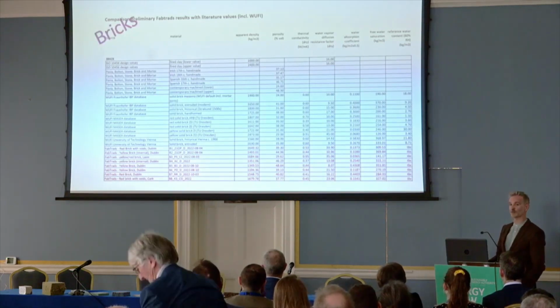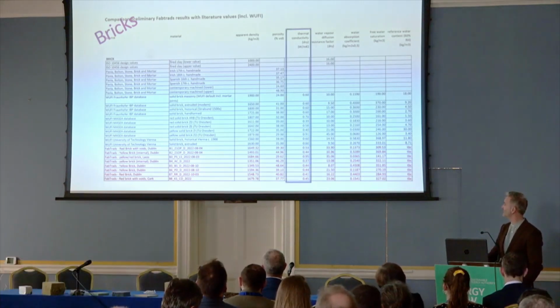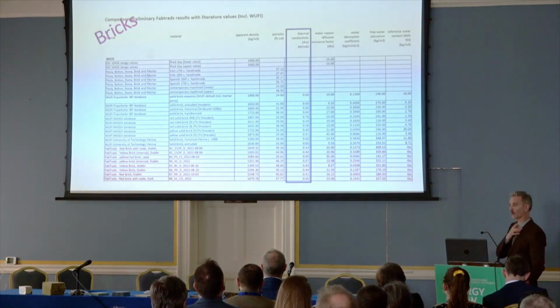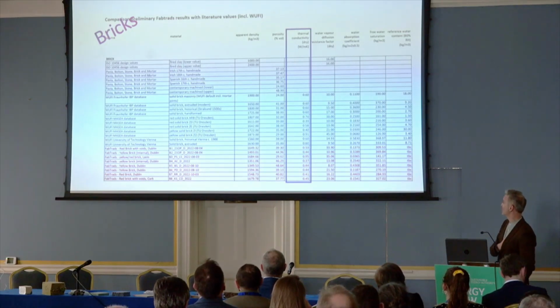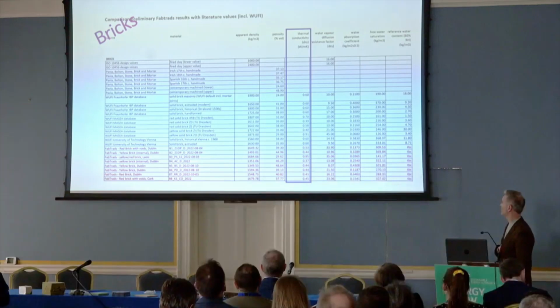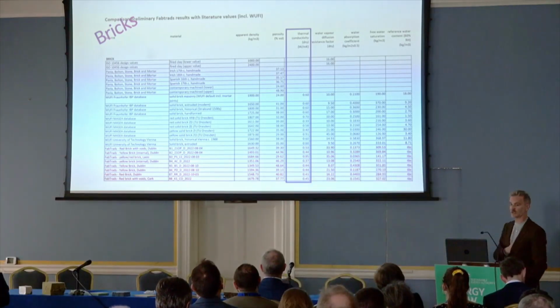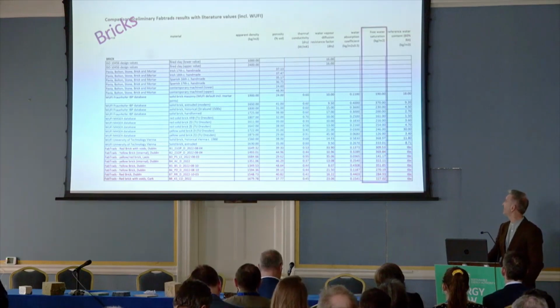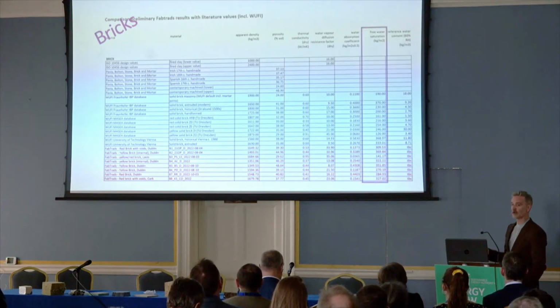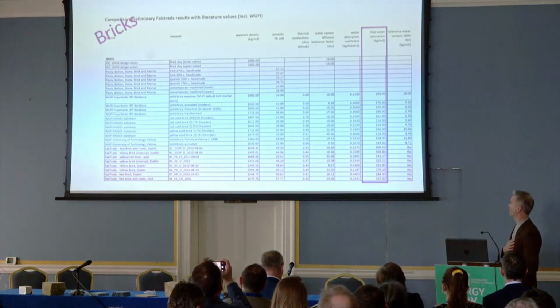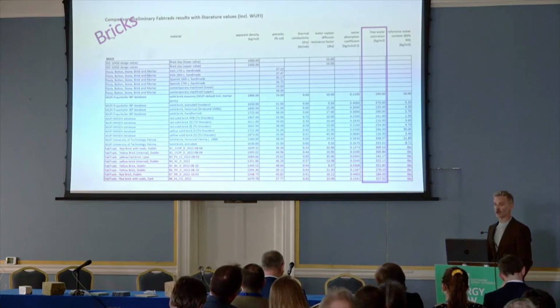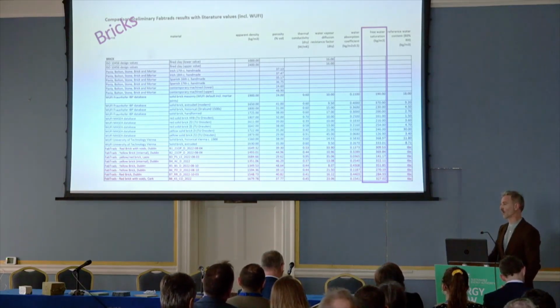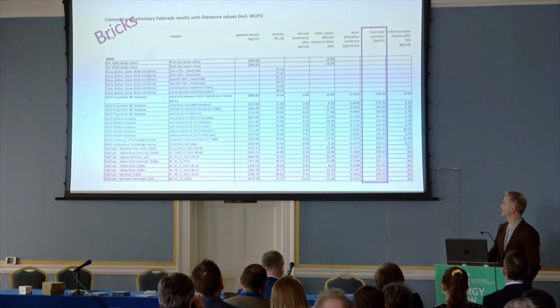We've tested a wide range of bricks. I think we've done 8 bricks at this stage. We're still searching for more, and I'll talk about that towards the end of the presentation. What we're seeing is generally a lower thermal conductivity than what's documented in the literature for the range of bricks that we have, primarily because the porosity is higher than the porosity of the bricks that are documented, particularly in the WUFI database. As a result, we are also seeing a much higher free saturation level, so more likelihood of the Irish bricks taking up water than those that are documented in Central Europe.